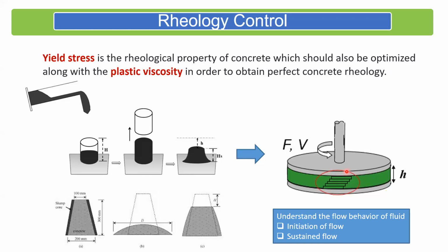And the key is to understand how it starts the flow and how it sustains the flow under an applied shear. So for that, we need this rheometer, which allows us to apply shear in a controlled way, measure the shear as a function of strain rate. So this takes us into understanding of the fluid flow behavior from the initiation of flow perspective and what is required to sustain flow. So this then gets tied into, once I can understand what it takes to initiate flow in the cement paste and then sustain the flow, then I can model, or I will be able to predict the behavior of concrete in our conventional slump cone test. And I can then start distinguishing between slump and flow. So this is the fundamentals of rheology and how rheology made entrance into concrete mix designs.